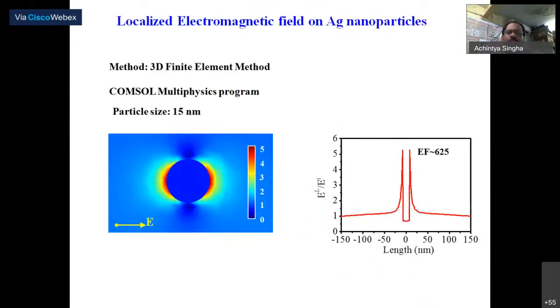So these are some simulation results showing how this enhancement, meaning the electromagnetic field, is localized on the surface. This is the COMSOL simulation, and you can see if there is a single particle, the strong red part is the localized electric field, and the right side graph shows the enhancement factor for a single particle. You can see the enhancement factor is of the order of 10 to the 3.